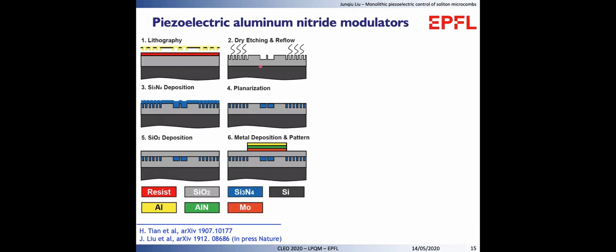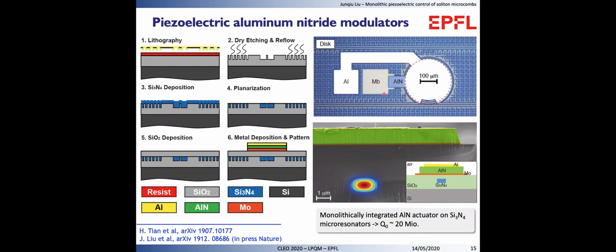In our work, we build a piezoelectric aluminum nitride modulator on our Damascene ultra-low loss silicon nitride photonic circuit. On the left is the fabrication process flow. The optical micrograph shows the disc-shaped aluminum nitride modulator covering the silicon nitride waveguide. The SEM image shows the sample cross-section. As we use thick silicon dioxide between the silicon nitride waveguide and the aluminum nitride modulators, the optical mode is far away from the metal, which maintains the low loss in the silicon nitride waveguide and keeps a high microresonator Q of 20 million.